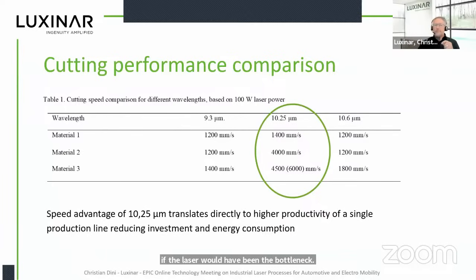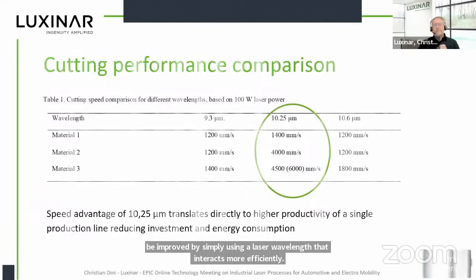At the same time, the same cutting process requires less energy. So the carbon footprint of that particular process can be improved by simply using a laser wavelength that interacts more efficiently, more effectively with the material.